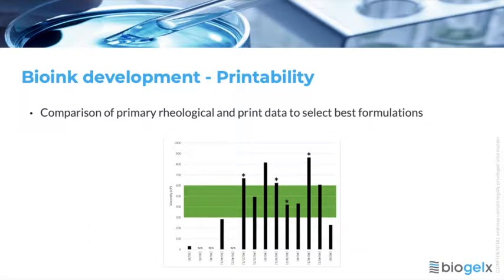The benefit of working on a small scale means that we can test a lot of formulations in a reasonably short amount of time. And in this example, I think it was 14 or 15 formulations that we were able to assess in the space of a week or two. And highlighted in this graph here is the green window of 300 to 600 centipoise, which we were aiming for. The starred bars are formulations of particular interest, which either fell within that viscosity range or came close to, and also showed good results in the filament and printability test.